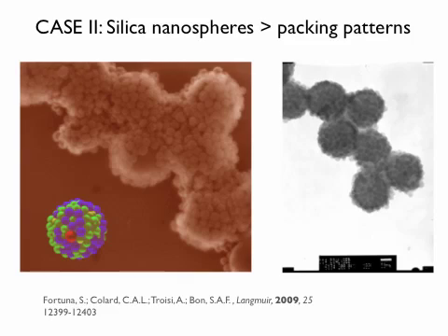So these particles were Ludox silica spheres of 25 nanometers, and they had a polydispersity index of about 14%, which means that we have to take into account that there's a size distribution over these small ones. So again, modeling comes in, and it's quite a fun story.